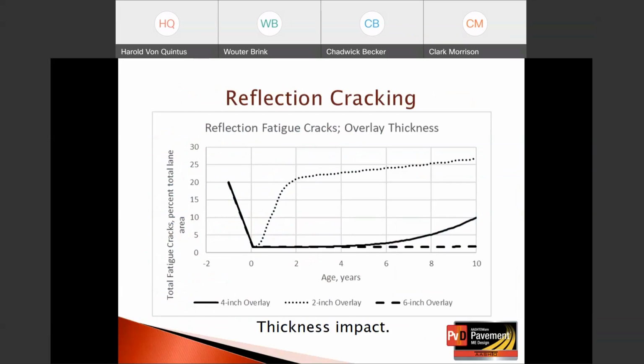And this graph or figure shows the reflection fatigue cracks for different overlay thicknesses. The solid line is a 4-inch asphalt overlay. The short dashed line is a 2-inch overlay, and the longer dashed line at the bottom is a 6-inch overlay. And you can see for fatigue cracks, overlay thickness, which we would expect, is very significant in delaying the occurrence of the fatigue cracks, and that's bottom-up fatigue cracks from the existing asphalt layer.